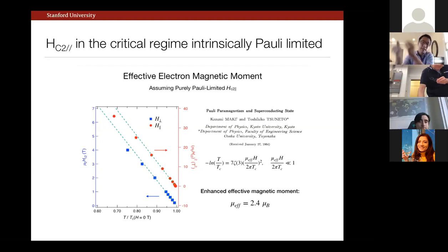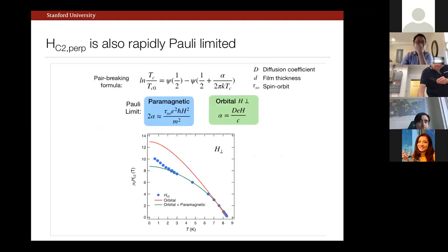But now let's stay in this perpendicular field direction and look more broadly at temperature. And this is the raw data here. This is HC2, again, in the perpendicular direction. Here's the linear regime I just emphasized to you. But as we go in temperature, it has this rather strange variation. And what we conclude by taking this classic analysis of thinking about pair breaking is that we're also rapidly Pauli-limited even in the out-of-plane direction.